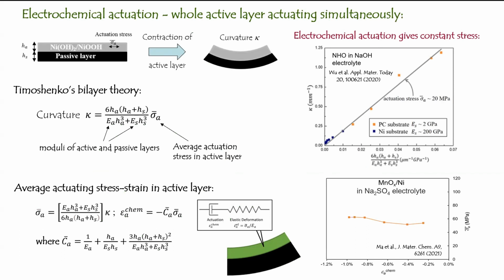This is always the system that we are considering. We have an active layer that can expand or shrink, supported by a layer that does not change. So when the top layer shrinks, it will develop an upward curvature. If you go back to the very old Timoshenko theory, more than 100 years old, that's also from our year 1 or year 2 mechanics course, a lot of those equations are very useful in this field, because the system is exactly a bilayer. The curvature from that theory is a bunch of constants depending on the thicknesses of these two layers and their Young's moduli. So for a given dimension or geometry and material system, that is a constant.